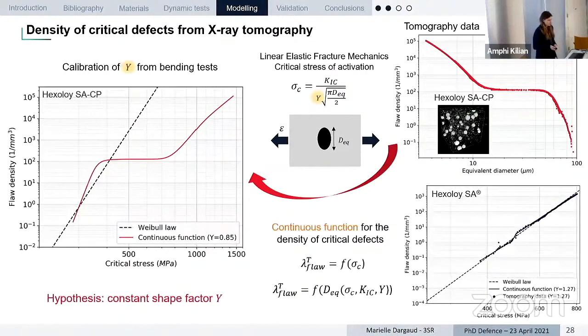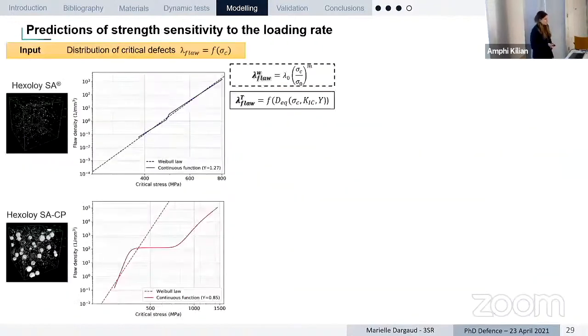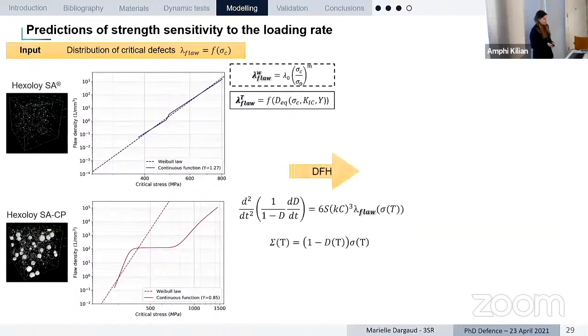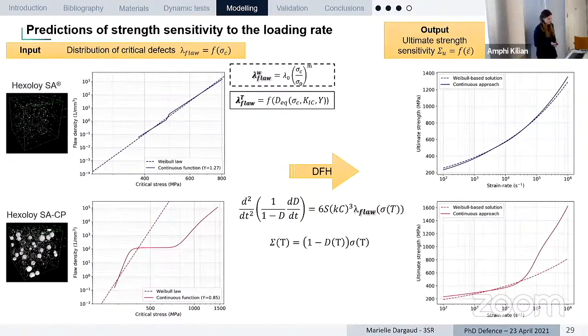So we did the same for the second material. Now, here we have the input of the DFH model. So it's for both materials, the distribution of critical flaws that we've just obtained. We can see that for the first material, we have almost the same thing between the Weibull approach and the continuous approach. So when we are going to apply the DFH model and the analytical formula to get the strength, we have almost the same results. However, for the second material, the large difference in the critical population of defects is going to lead to a big difference in the strength sensitivity to the loading rate. And you can see here that at high strain rates, we actually have a very high increase of the strength of the material, which is not captured in the Weibull approach.